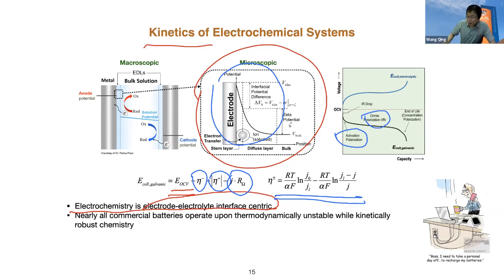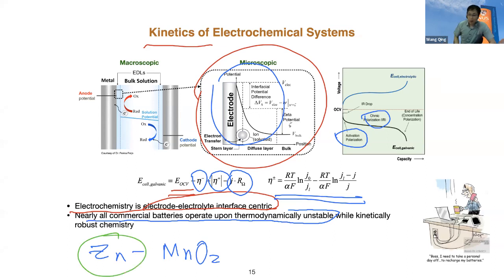And not only that, if you look at the different battery technologies, from the dry cell to the lead acid battery, to the nickel cadmium battery, all the way to the lithium battery, look at the materials we use in a battery. Nearly all of these batteries operate at some thermodynamically unstable condition. If you look at the dry cell, we use zinc and manganese dioxide. The zinc potential, thermodynamically, obviously is not stable. It's never in contact with water because zinc always tends to reduce water to form hydrogen. Another example is the lithium-ion battery. Look at the negative electrode material, the potential is so negative that the different solvents in the electrolyte get reduced. So thermodynamically it's not stable.